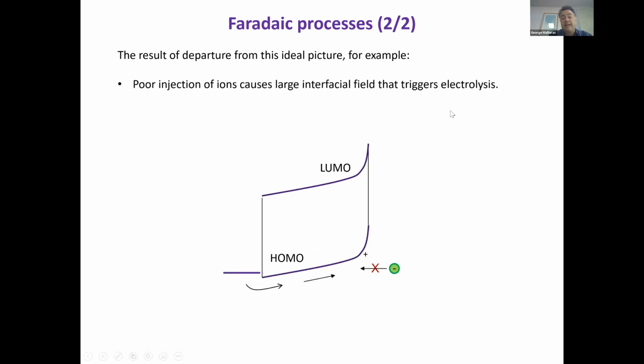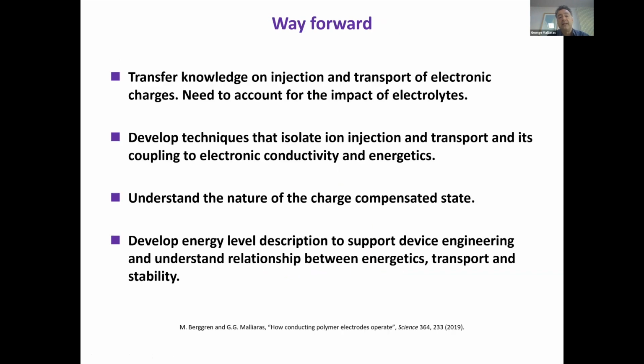You could have a situation where ions cannot penetrate into the film, but rather butt against the surface. And that causes very large electric fields here that will give rise to electrolysis. That's again a non-ideal behavior. It departs from the ideal example I showed you earlier, and it would lead to Faradaic response. So using this framework can be very powerful to understand these phenomena. And there is a clear way forward.